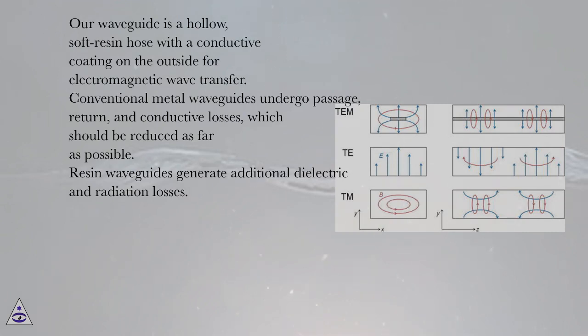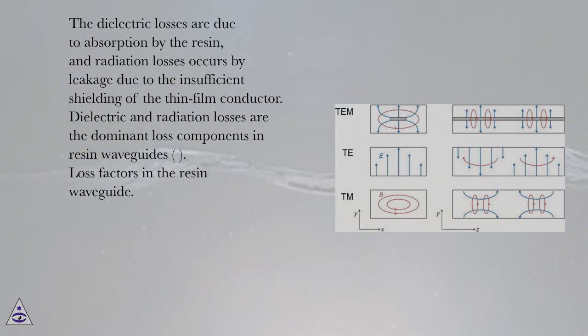Conventional metal waveguides undergo passage, return, and conductive losses, which should be reduced as far as possible. Resin waveguides generate additional dielectric and radiation losses. The dielectric losses are due to absorption by the resin, and radiation losses occur by leakage due to the insufficient shielding of the thin film conductor. Dielectric and radiation losses are the dominant loss components in resin waveguides. Loss factors in the resin waveguide.